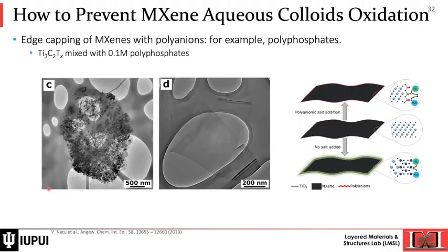There's another study that came up from Drexel, from Professor Barsoum's group, that showed that MXene oxidation starts from the edges, as we briefly mentioned previously. So that's the defects area. So if we can basically protect the edges, then MXene oxidation will be just prevented for a longer time. Here you can see that this is a MXene flake in TEM after storage, that you can see all these black dots are oxide nanocrystals forming. And here's the one that was capped. So edge capping with, for example, here only 0.1 molar of polyphosphates.